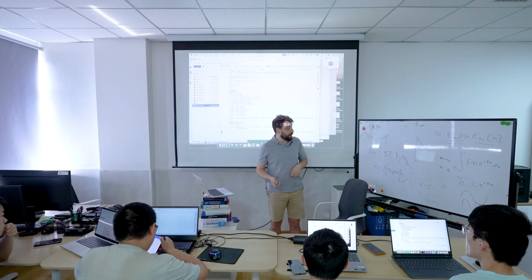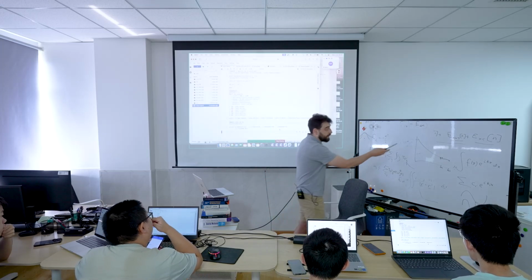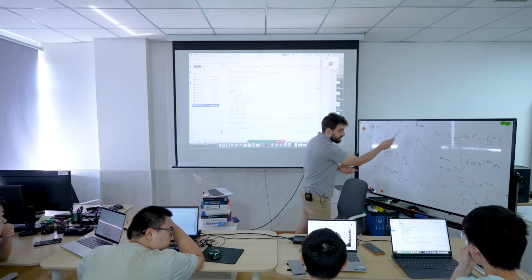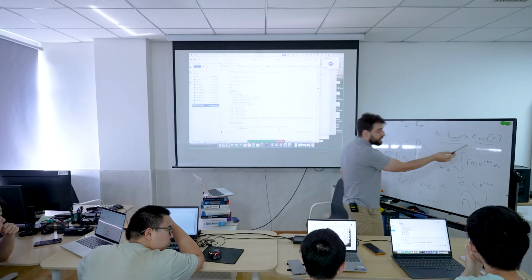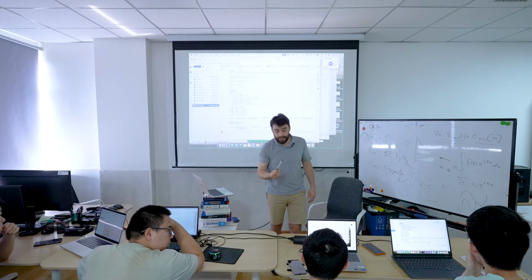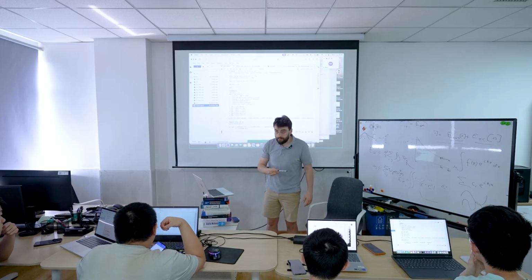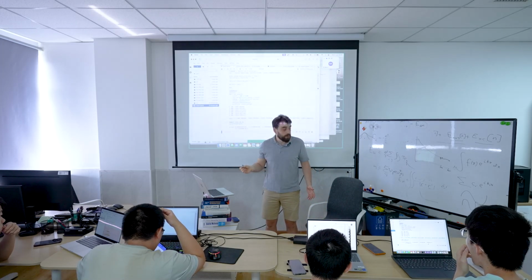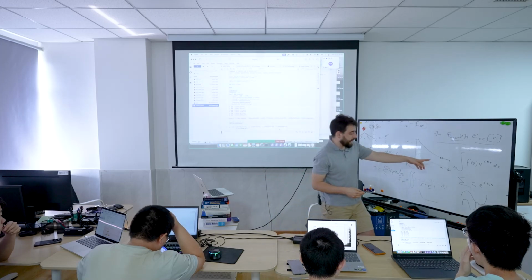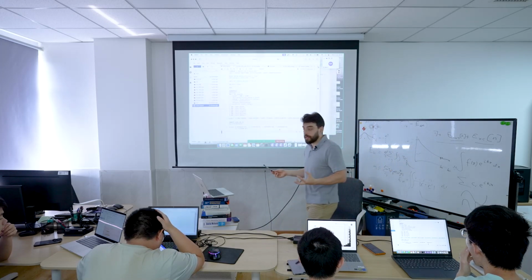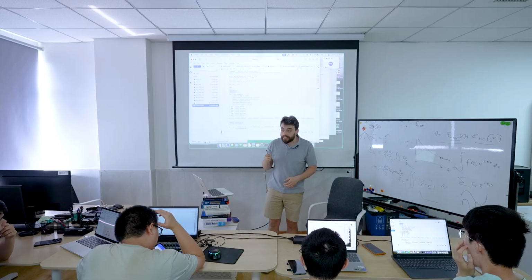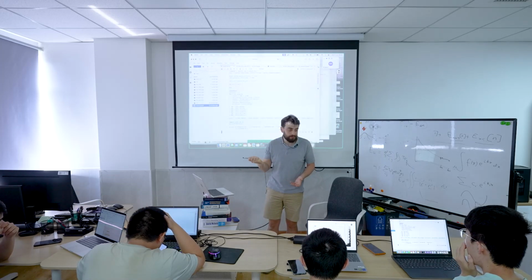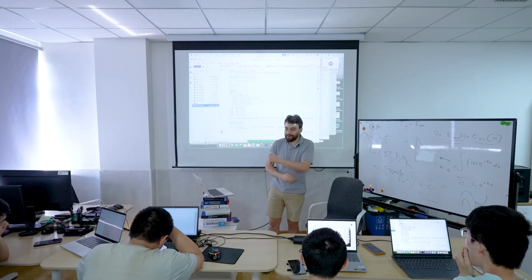Because we have to remember that the difference between real quantum mechanics and DFT is that DFT also has an error associated with the exchange correlation functional. So if we're using an LDA functional on an oxide, and we've converged our basis set down to 10 to the minus 3 or 10 to the minus 4 eV, you're just very precisely predicting the wrong result, right? So it's not very helpful.